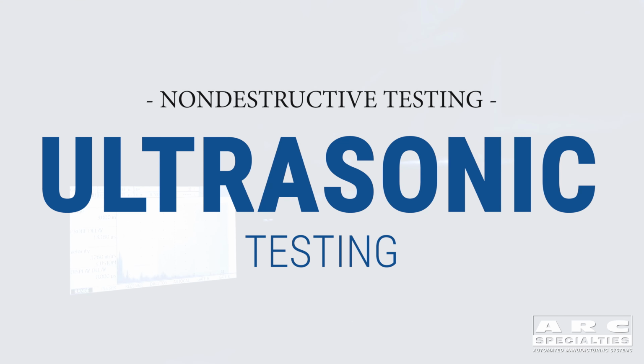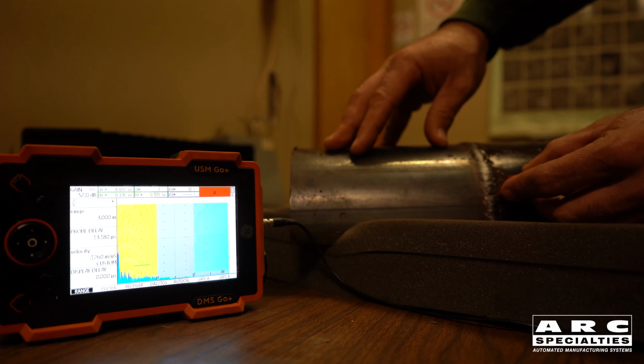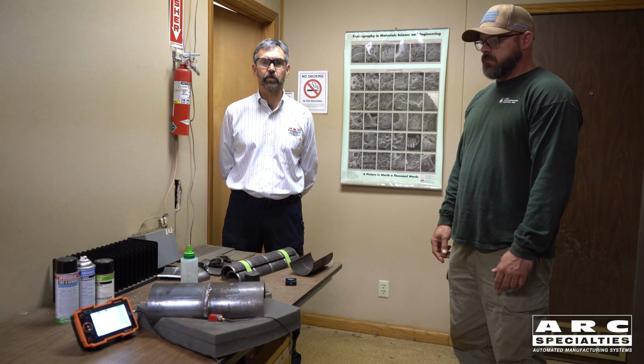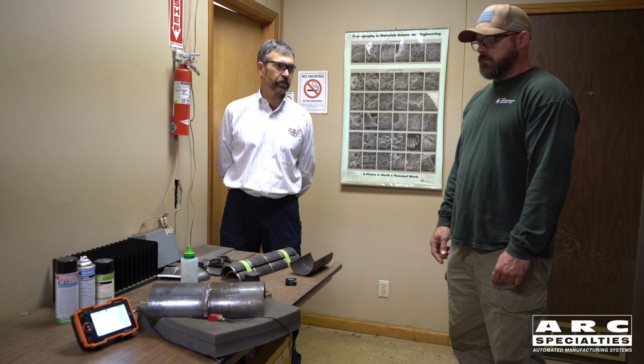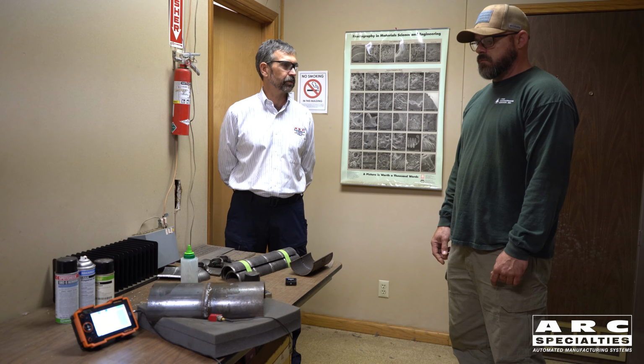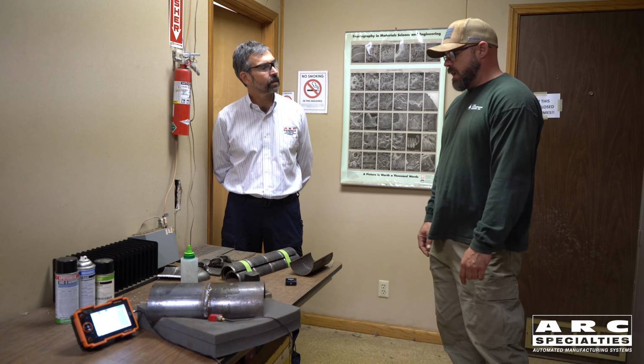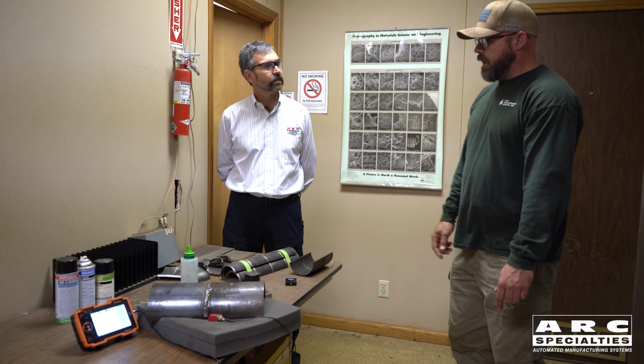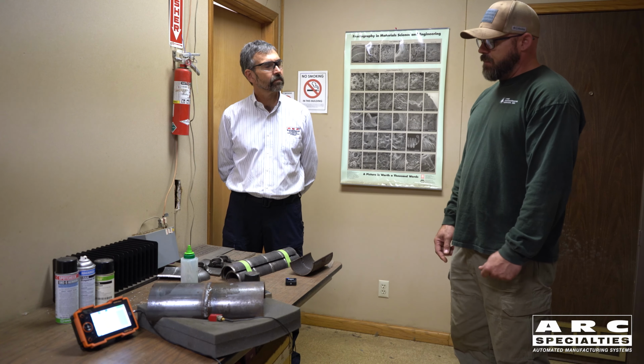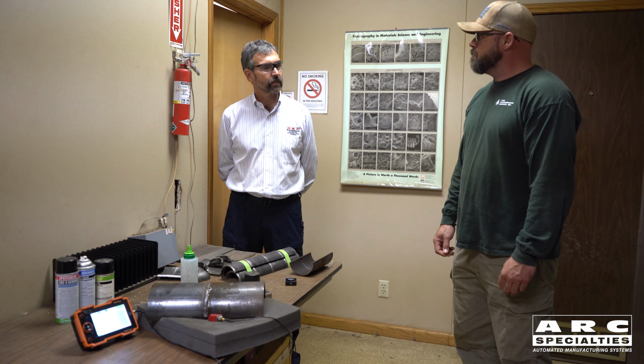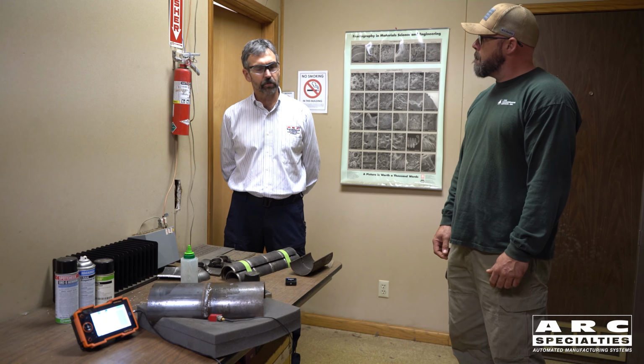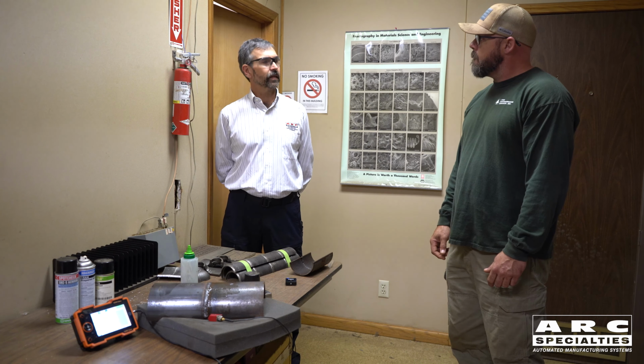Another non-destructive testing technique we use is ultrasonics. One of the advantages of ultrasonics is you can find subsurface indications. Jason's going to demonstrate this technology to us. What kind of sample you got here? I've got a sample here that is an 8-inch pipe that has lack of fusion and lack of penetration at the root. And so this technology will be used to inspect the inside of the pipe from the outside.